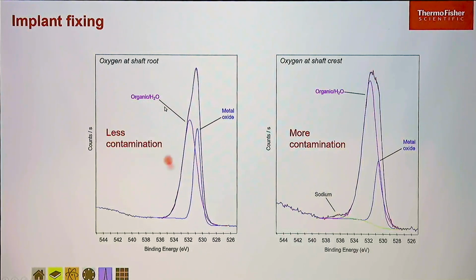And in the oxygen, we can see less contamination in the root compared to the crest. Now, this is probably just due to the handling. When you're picking these up, you're going to touch the crest rather than the root. So I suspect the oxygen and carbon contamination there is just due to handling, or even the packaging it's been in, rubbing against the plastic, it will pick up more plastic contamination on the surface than it would in the dips in the screw.